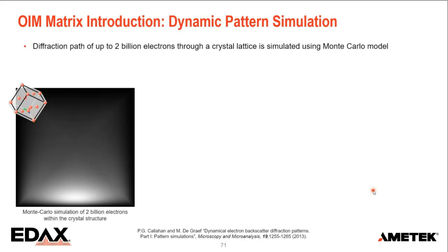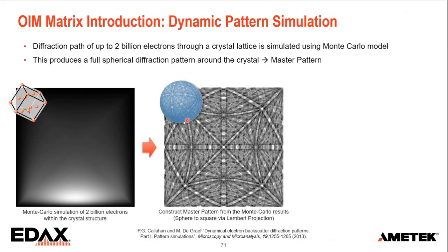And what we do there, we generate simulated EBSD patterns. That tool has been implemented in the software, and it works by making a cloud of up to 2 billion electrons. You specify a crystal lattice, and you let those electrons travel from a center point outwards in all directions. And when you do that, you can get diffraction in all directions, so we know where the electrons are going. We can make that into a flat projection here by the Lambert projection. That is an EBSD pattern of an entire sphere. This is what we call a master pattern.